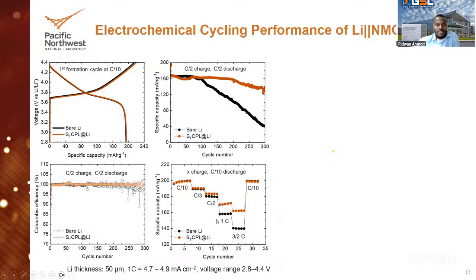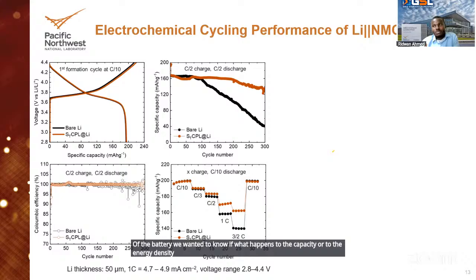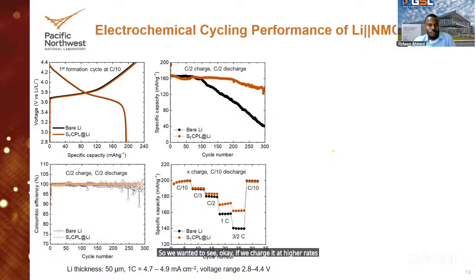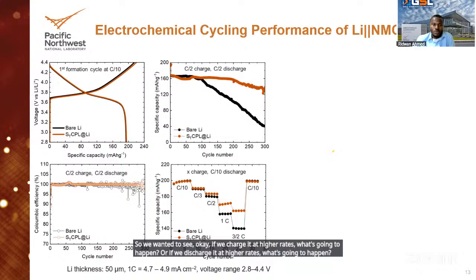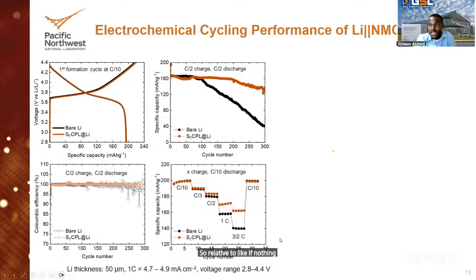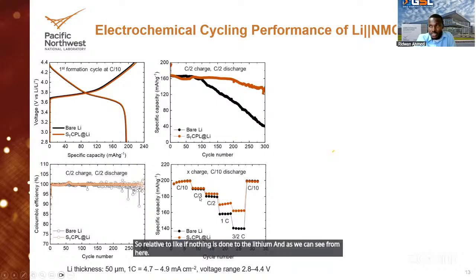The last graph here is the kind of test we conduct to check the rate capability of the battery. We wanted to know what happens to the capacity or the energy density when you charge it very fast, because typically when you charge a battery very fast, it tends to lower the capacity of the battery. So we wanted to see, if we charge it at higher rates, or discharge it at higher rates, what's going to happen relative to if nothing is done to the lithium. As we can see from here, as you continue to increase the charge rate, the capacity decreases for both, but it decreases more with the bare lithium than the protected lithium.